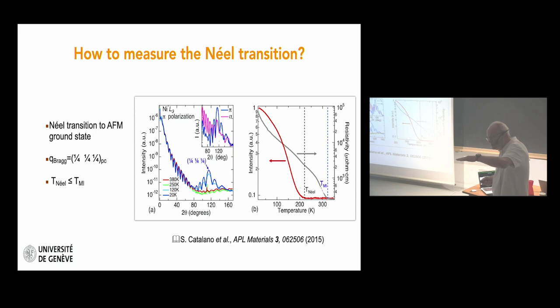And this is what you see here. You have to turn your sample to access the 111 planes. But if you do this, you see here the intensity as a function of 2 theta, and this peak here is a 1/4, 1/4, 1/4 peak, which is a signature of the magnetic order. And when you see this peak, you can follow this peak as a function of temperature.